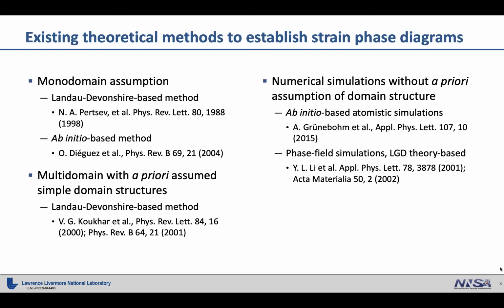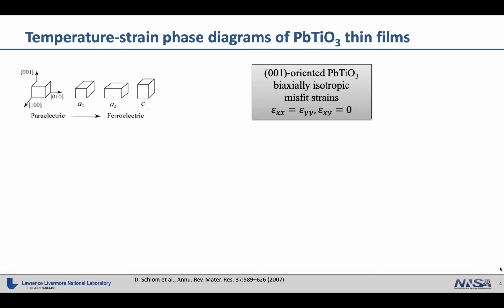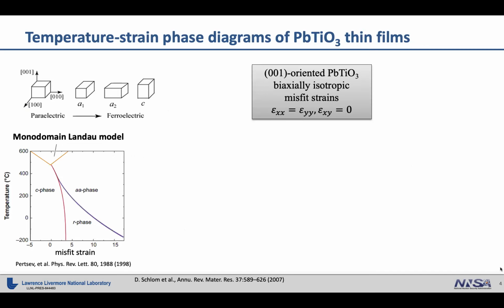There are a few existing theoretical tools if we want to calculate a strain phase diagram of ferroelectric materials. Some of them are based on some a priori assumption on the domain structures, while some do not need this assumption but require extensive numerical calculation. Let's take the lead titanate 001 oriented thin films as one example and see how these different methods perform. With the monodomain model, they can predict the phase diagram like this for lead titanate. However, as we know, the rhombohedral or AA phase in lead titanate thin film has never been really observed in experiments.